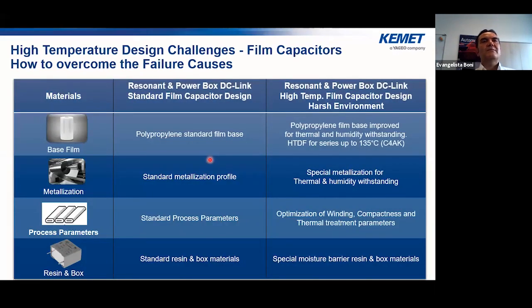Here we can summarize the actions adopted by KEMET in order to have this series at higher temperature. For the series using polypropylene, we have used high grade polypropylene up to 125 degrees. But for the power box capacitors up to 135 degrees, we have used a new film called high temperature dielectric film. About the metallization, a special metallization for thermal and humidity withstanding has been adopted. From the process point of view, the parameters of the winding compactness and thermal treatment have been adapted. Last but not least, KEMET has also studied a special enclosure, considering the proper box material and the proper resin.